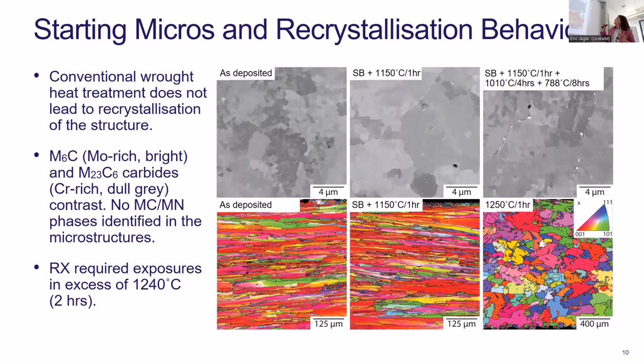And then following the two-step aging, what we see is M6C, the bright phase there along the grain boundaries is a molybdenum-rich M6C carbide. And in between that, we've got M23C6. Importantly, we don't see any MC carbides, so no MC or carbonitrides of any sort, monocarbonitrides of any sort, which is quite common in both the E-beam material and the wrought material.